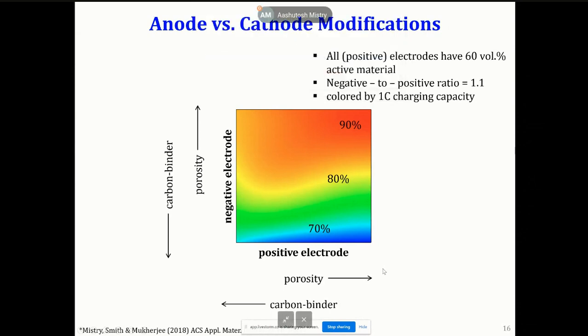So the way I'm showing these plots is we are fixing the amount of active material, and then we are changing the carbon binder and porosity volumes. If that's the case, then by increasing porosity and decreasing carbon binder, you would be able to get higher capacities. Similarly, if you fix porosity and now play with active material and carbon binder, then you would get a better capacity by going to higher active material packing, and you would only need a little bit of carbon binder to give the relevant electronic conduction that you need.